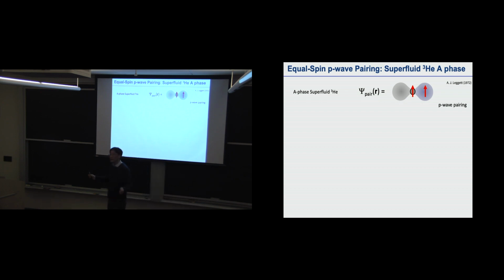However, in this particular case, they interact because it's neutral - they interact with very short-range interactions. To mediate this pairing with short-range interaction, it turns out this superconducting helium-3 utilizes p-wave pairing as its pairing mechanism, which means there is a tendency that the spin can be aligned in the same direction. It can be spin triplets, right?